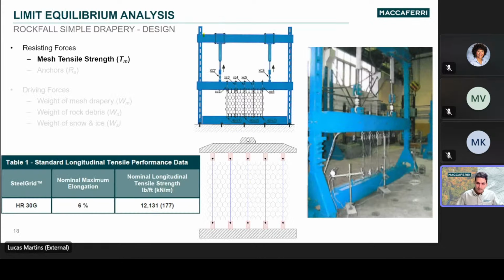So, the tensile strength of the mesh. Again, I said that it primarily functions along its longitudinal direction, so the tensile capacity is a critical design parameter. The photos and diagrams here show a standardized test setup used to measure the longitudinal tensile strength of the mesh. The mesh is clamped and loaded until failure. For example, our SteelGrid HR30G, a commonly used drapery mesh, has a nominal tensile strength of 12,000 pounds per foot, and it breaks at an elongation of about 6%. This strength value can be directly plugged into the limit equilibrium model, but its elongation is an important design consideration that's usually overlooked.